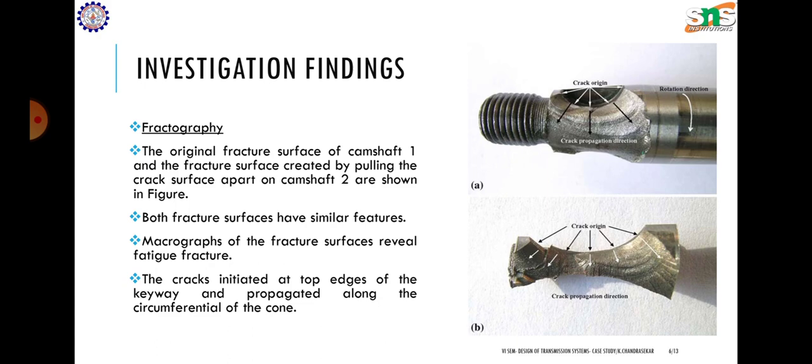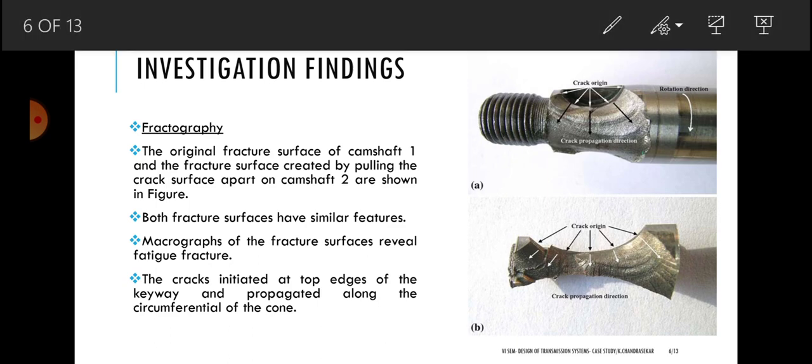According to the curvature of the beach marks, the crack initiated at the top edge of the keyway and propagated along the circumference of the cone.